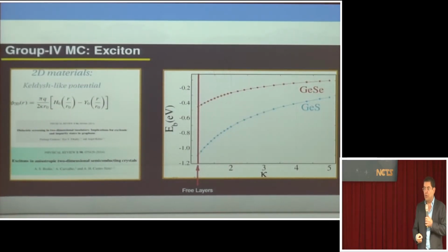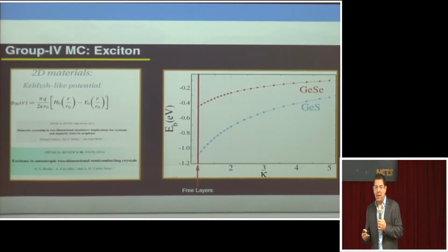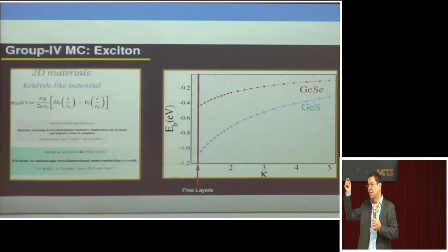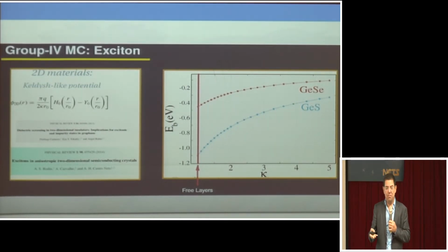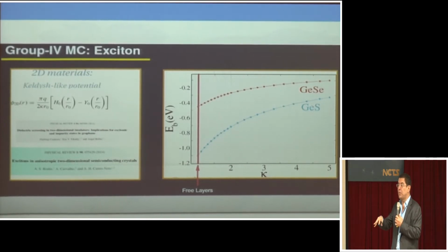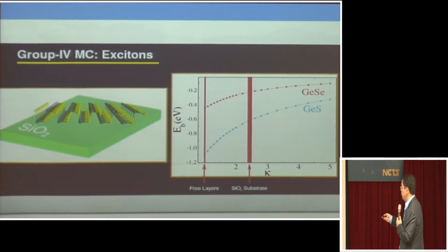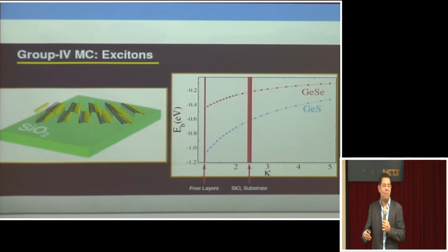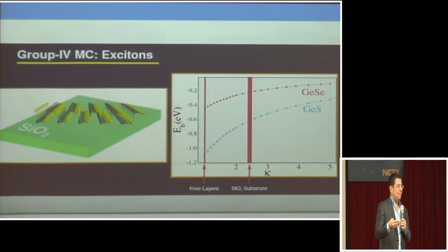Not only that, as I told you, we never do experiments with these materials in empty space. Nobody goes in the space shuttle, exfoliates graphene in the vacuum and does that. We need substrates. So the dielectric environment becomes extremely important. This is an example of the excitonic energies for these two materials, germanium selenide and sulfide, as a function of the dielectric medium, the substrate where you put these materials on top. This is what happens in vacuum, but if you have a silicon oxide substrate, the binding energies change tremendously, again because of the way the electric field is modified by the presence of the dielectric medium.